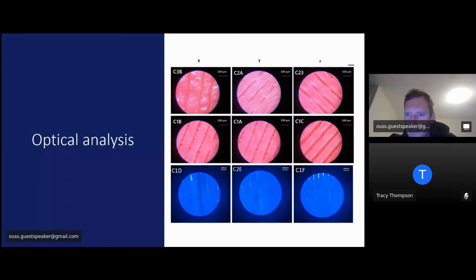It looks like there's been some outgassing going on, and potentially what's happened here is some of the gases in the 3D printed part, as it's been printing, have escaped, and the total volume that's being used by that part in the extruded material has reduced. So the volume of material is reduced because it's outgassed slightly. And what that may have done is just distorted the part and made it slightly more brittle. As you can see from C2E, the compressive one in the middle there, it looks very brittle, and it looks like something that's seriously gone wrong, which is very interesting, because that's in the exact same spot each time for each sample, which is dead center in the middle of the part.